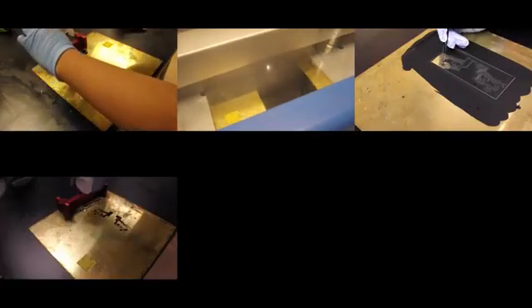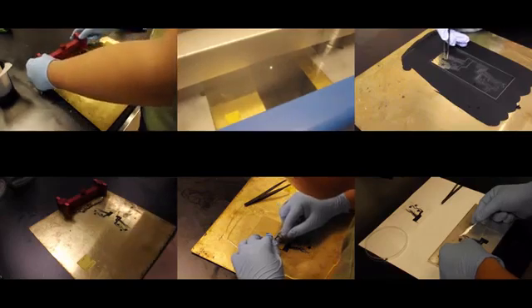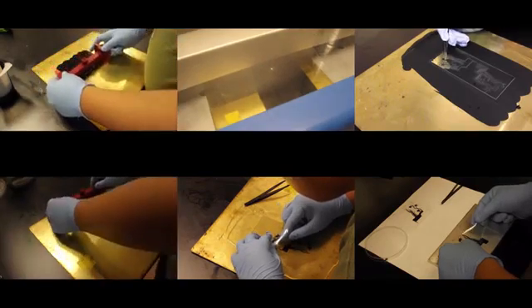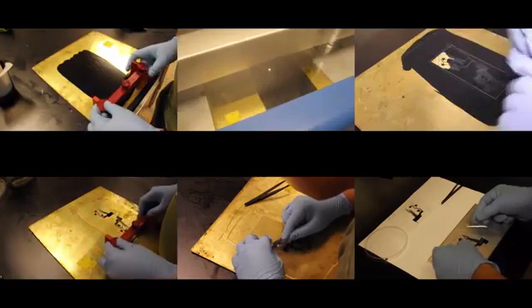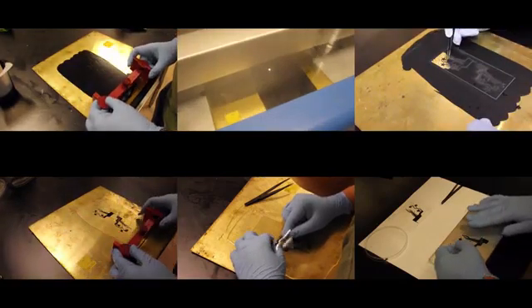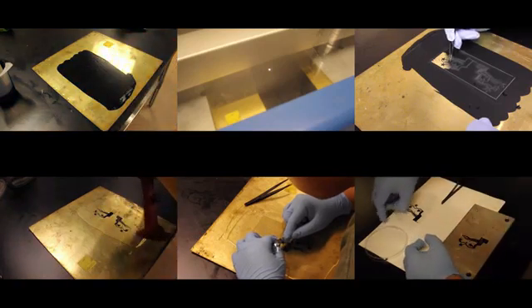iSkin builds on recent advances in material science. The sensor is a sandwich composed of multiple layers of silicone. Non-conductive parts are made of transparent PDMS, while conductors are realized with carbon-doped PDMS. Both materials are biocompatible, flexible and stretchable. The thickness of the sensor surface is between 0.3 and 0.7 millimeters.